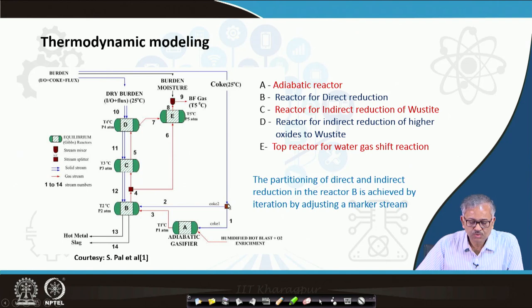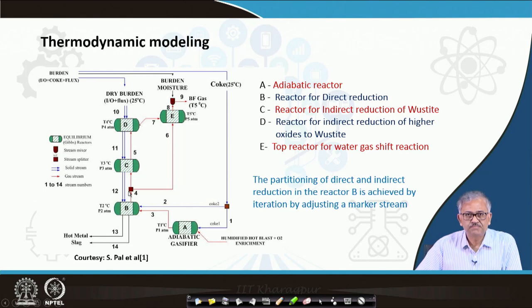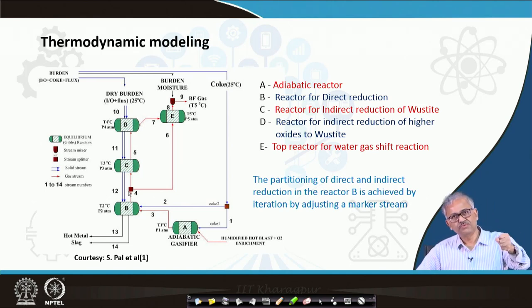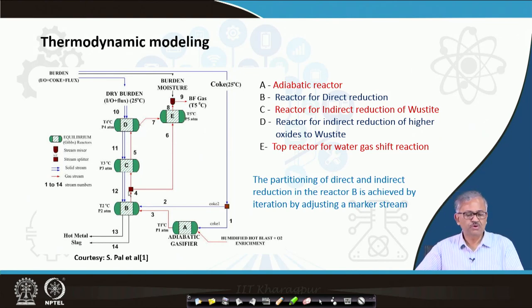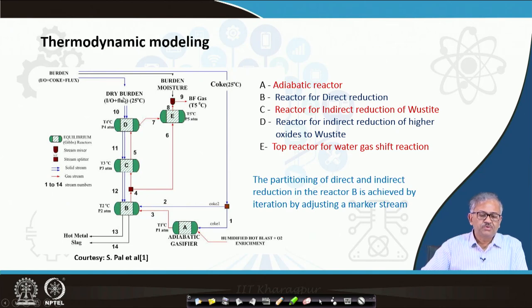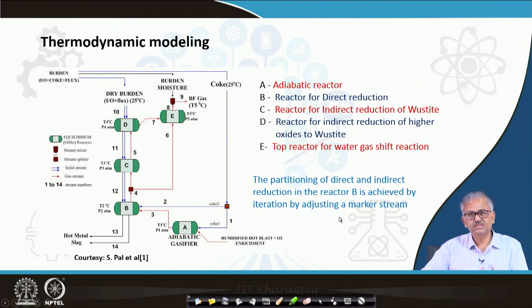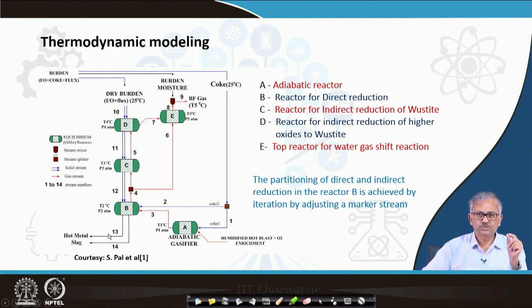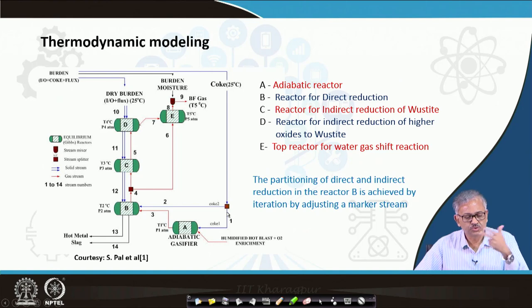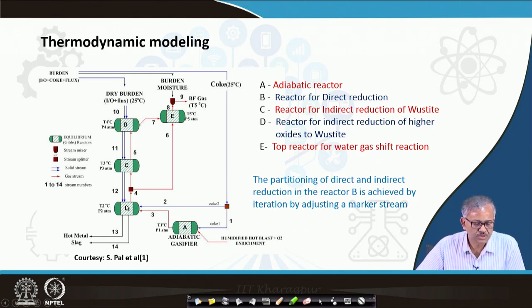The coke is split into two parts — coke 1 and coke 2 — for direct reduction and indirect reduction. How much goes to each is decided by a solid stream marker. You give a certain amount of Fe₂O₃ and you must get a corresponding amount of iron. The splitting of coke is determined iteratively: when the iron output is fixed by the mass balance marker, you can stop the iteration. So iteratively you calculate what will be the partition of coke for direct and indirect reduction.